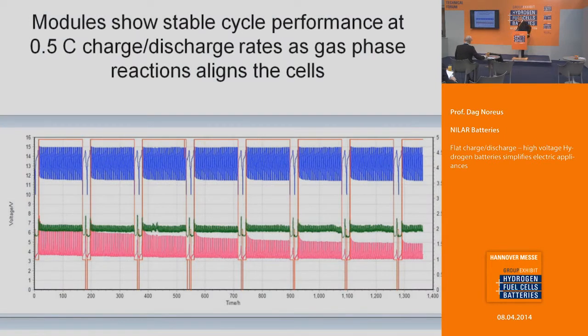So this is a somewhat complicated picture, but this shows the cyclic stability of these modules. They are cycled at 0.5 charge and discharge rates. It's sort of 2 hours charge and 2 hours discharge. And what you see here is the voltage. So this is the charging voltage, which goes up to 15 volt, and the discharge falls down to 11.5 volts here. And then we do some capacity measurements in between. So this cycle is very stable. And also the discharge end voltage you see here is very stable.